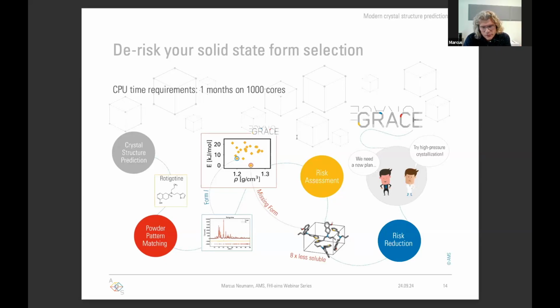Often they're experimental forms, but their structures may not have been solved. But if they crystallize, then a powder pattern can readily be measured. And so it's easy to compare the predicted crystal structures against experimental powder patterns. For the case here, rotigotine, which is one of the disappearing polymorph accidents, today we would readily realize that the experimental powder diffraction pattern actually corresponds to the blue open circle, so it's called form number 1 for the pharma customer. And we would also see that there's actually a much more stable form out there, here represented by the red circle, that has not yet been discovered.